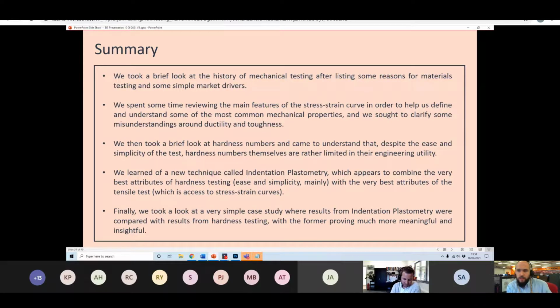Does your method cope with surface and case hardening, and can it measure core properties in this case? Another really good question, and the answer is this all depends on scale. So let's suppose we've got a case hardened layer that is hypothetically 10 microns thick, but we are indenting to 250 microns. Then the contribution of that 10 micron thick layer to the observed behavior is going to be quite small, almost negligible actually. And what we'll really be interrogating is all of the material beneath that case hardened layer. So the stress strain curve that we pull out or infer is really the underlying or the bulk mechanical properties beneath the surface layer.